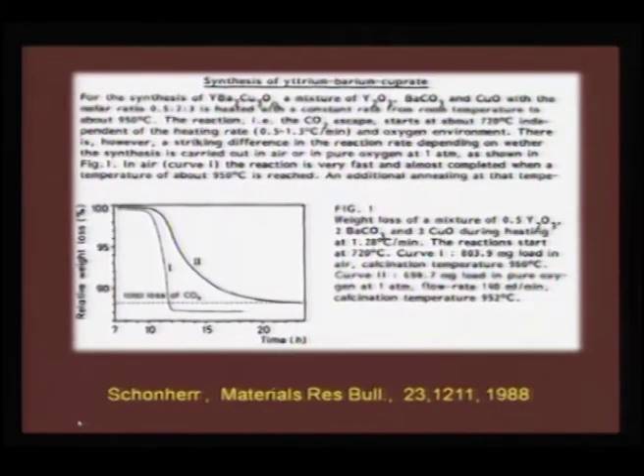This is a cartoon where you can find out how critical making this material is, and as you would see here, this is a thermogravimetry, which just gives you an idea how the solid state reaction happens. You take 0.5 moles of yttrium oxide, 2 moles of barium carbonate and 3 moles of copper oxide, and this has to be ground intimately for many hours, and then once this is intimately mixed, you can heat this material from room temperature up to 950 degrees C, and during this time you would see carbon dioxide going out of barium carbonate. Other than that, all the other components are oxides.